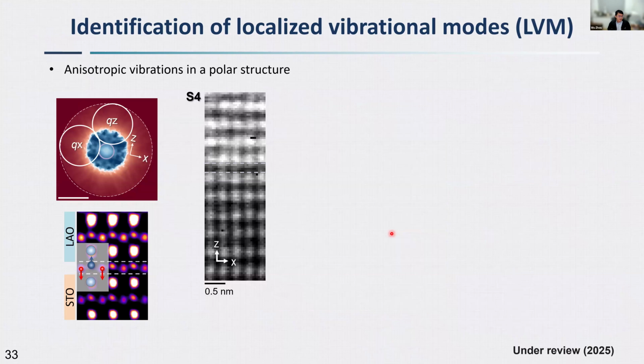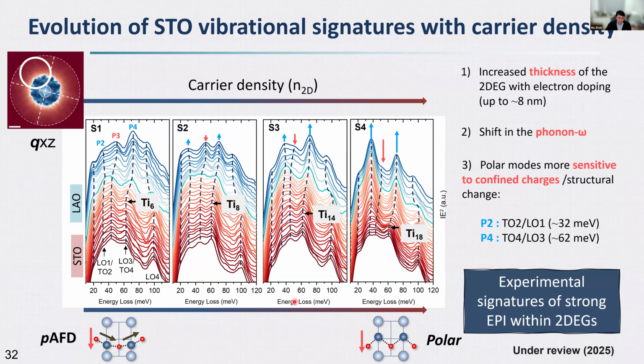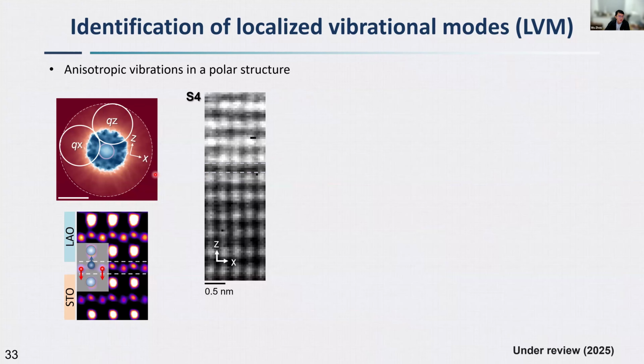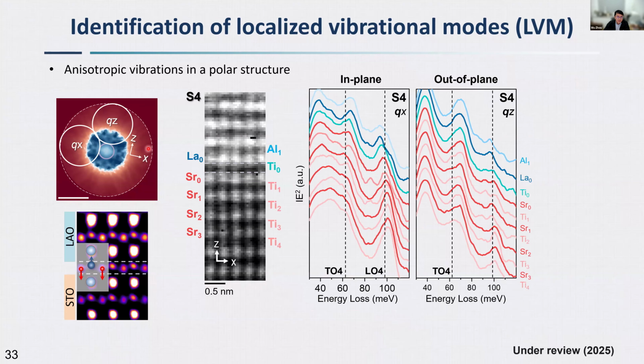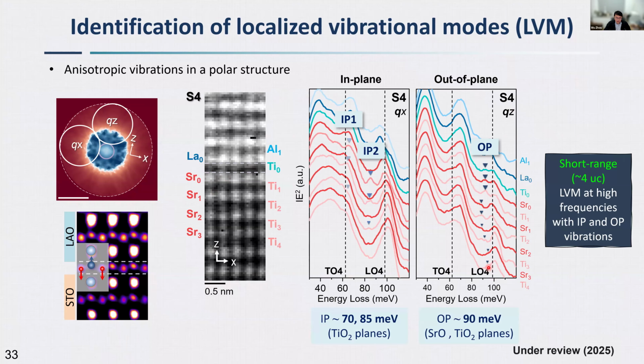So finally, we look at the new vibrational modes that emerge at the interface in addition to those intrinsic STO vibrational modes. We need to use momentum selection to look at the modes parallel or perpendicular to the interface. In this case, we're looking at the highest doping sample, and we look at the vibrational signals atomic layer by atomic layer. Here you will see a few additional new modes that are localized at the interface, and they fade away when you go about four unit cells away from the interface. And this corresponds to the out-of-plane vibration and in-plane vibration when we use different collection geometries.